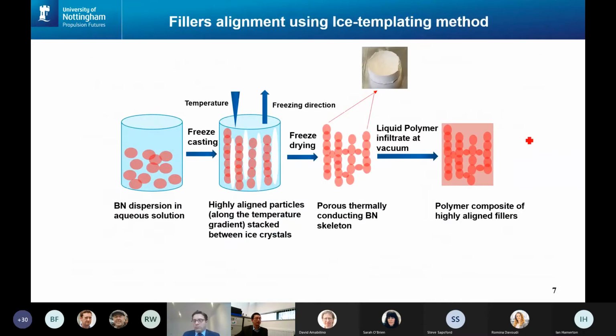So the method we chose is called the ice template method, or sometimes also called the freeze casting method. First, we produce a dispersion of hexagonal boron nitride, putting these boron nitride platelets inside a water-based solution. After that, we put this container in a very cold chamber, and the bottom of the chamber is cooled by liquid nitrogen. Then we can create a temperature gradient, very low at the bottom and slightly higher at the top.